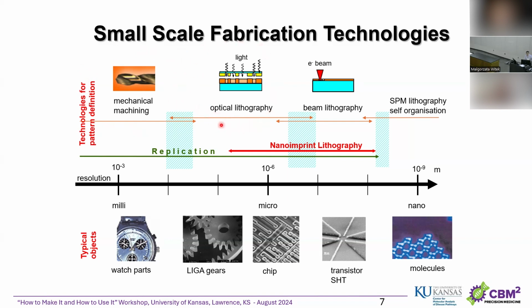And then the optical lithography. Depending on the wavelengths of the beam used, the smallest structure ranges from micron to sub-micron. Then with E-beam lithography and focused ion beam, you can produce structures down to around 10 nanometers. With focused ion beam milling and e-beam lithography, there have been papers which show structures in the range of 2 nanometers, 3 nanometers. But this is a very unusual case. Routinely, those techniques are used to produce structures in the range of tens of nanometers.